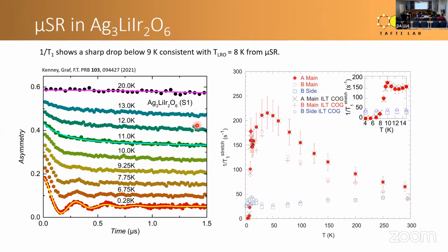All right, my group also does other experiments. We do mu-SR experiments, which is a local probe of magnetism. Here I show an example of mu-SR data in silver lithium iridate. In mu-SR, you send a polarized beam of muons. The muons implant in the material, and they decay after 2.2 microseconds.